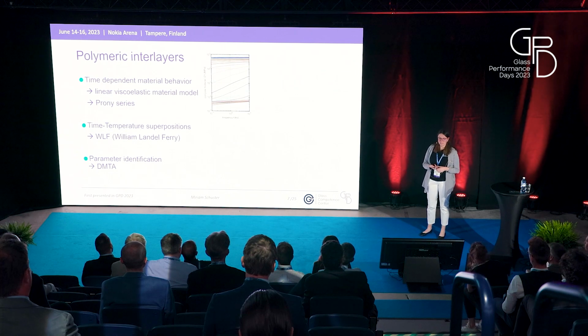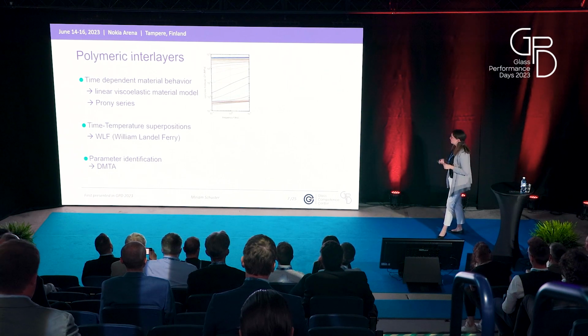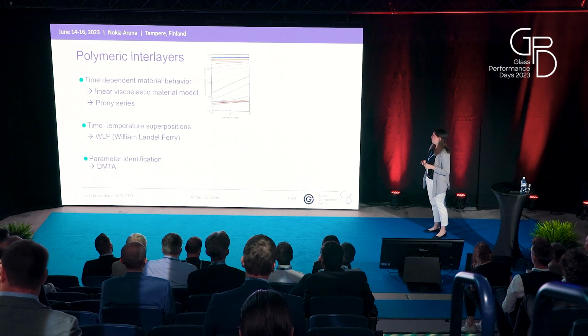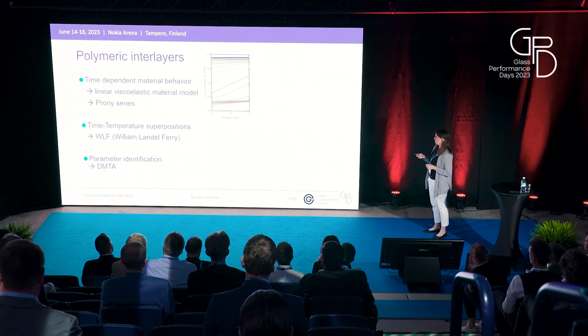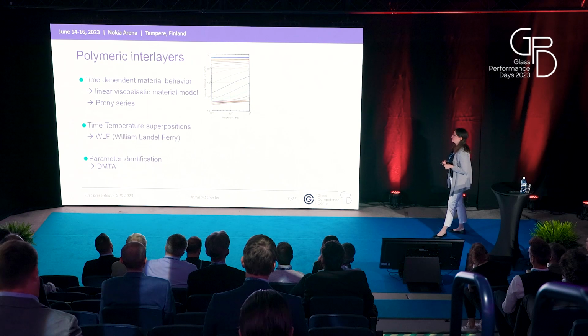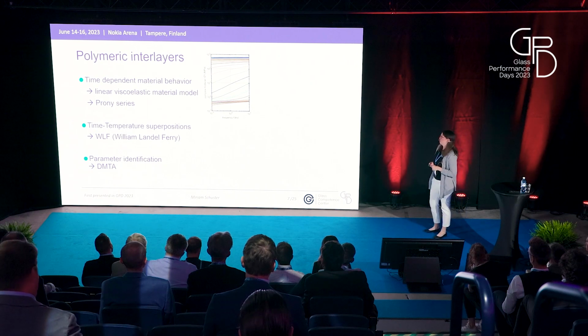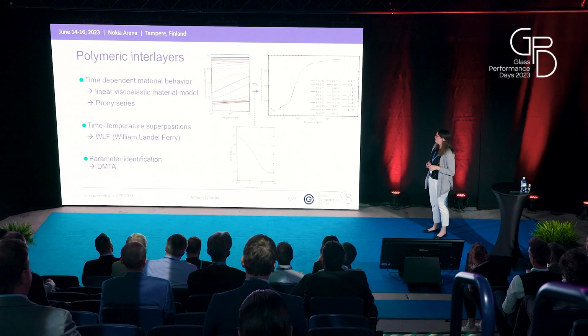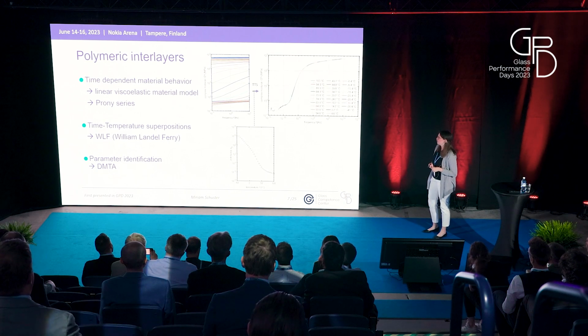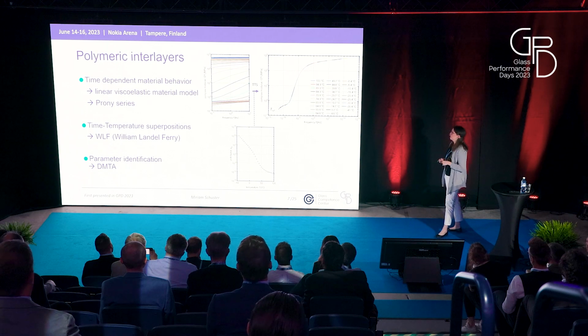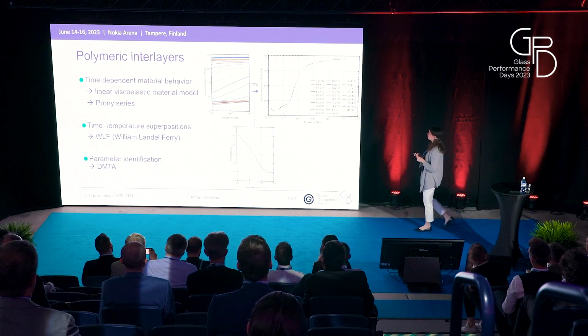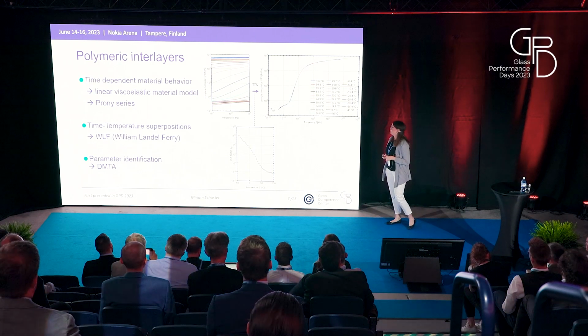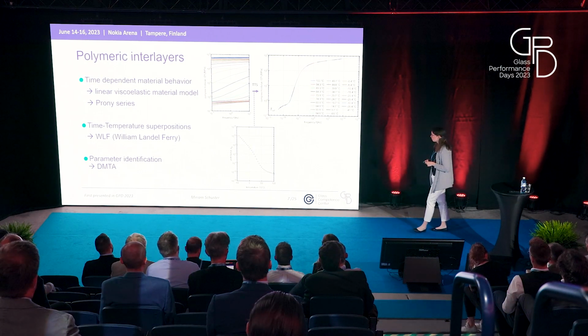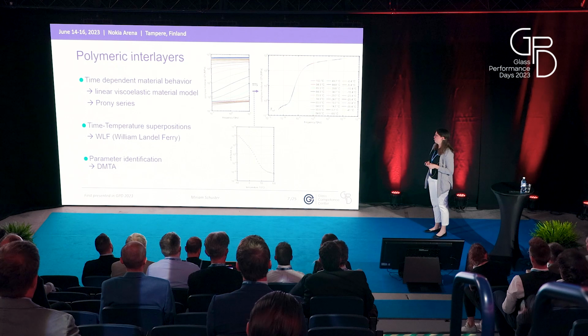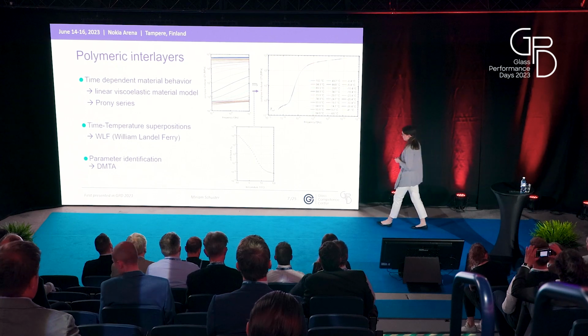The result of such tests are a bunch of curves. Here we see shear modulus values in dependency on frequency, and each of the lines is one curve at a specific temperature. And with these curves, we can generate a master curve by shifting them purely horizontally, and this master curve is then valid for a certain reference temperature. And the shift factors that were needed to generate these master curves are depicted in the graph on the bottom.